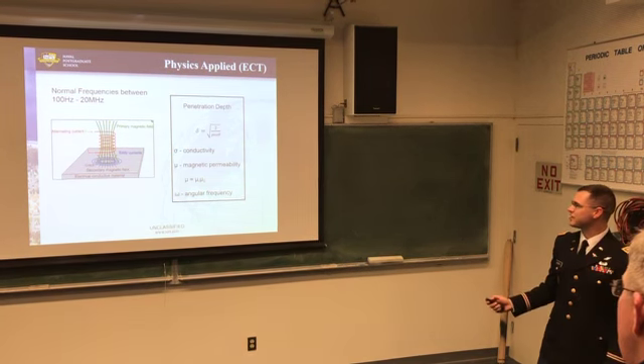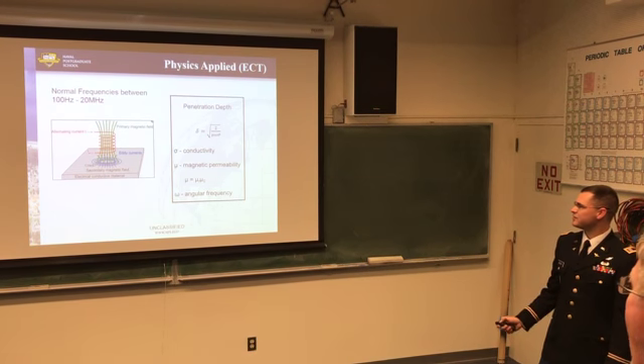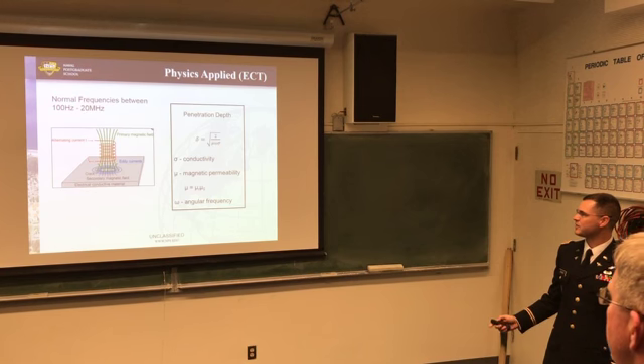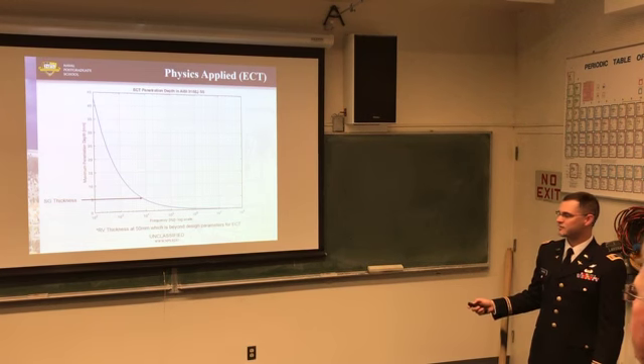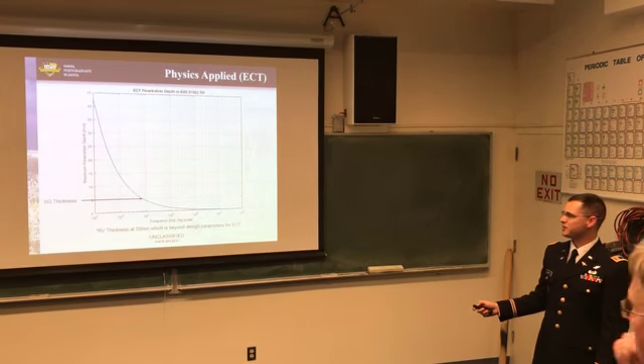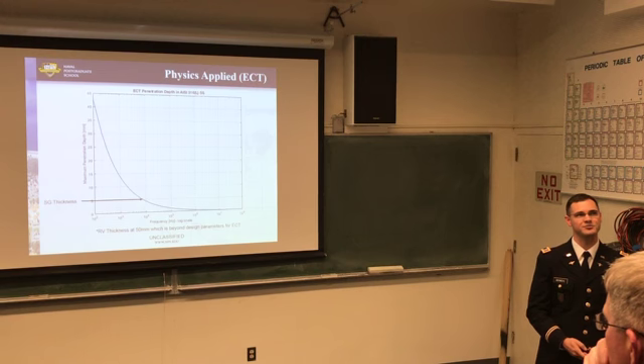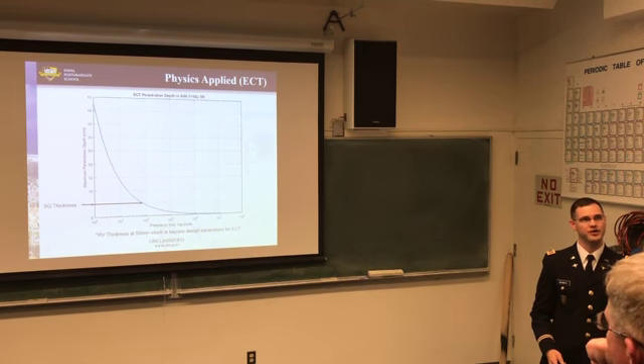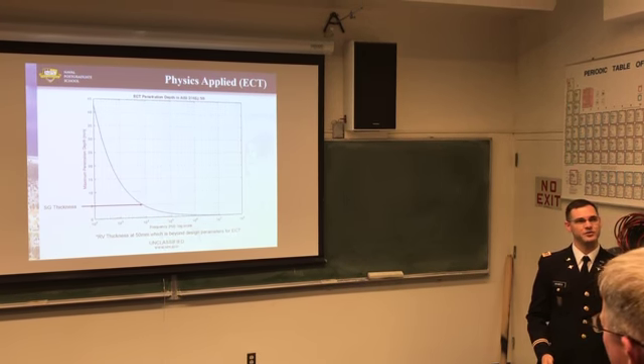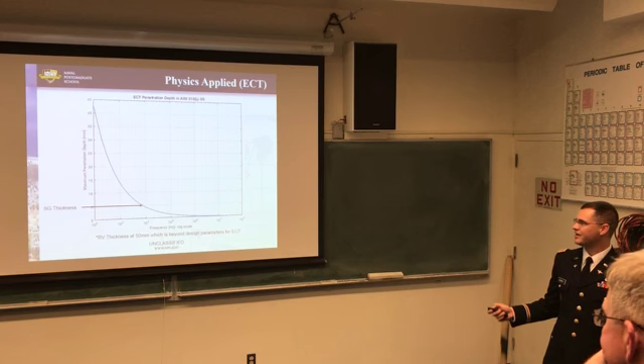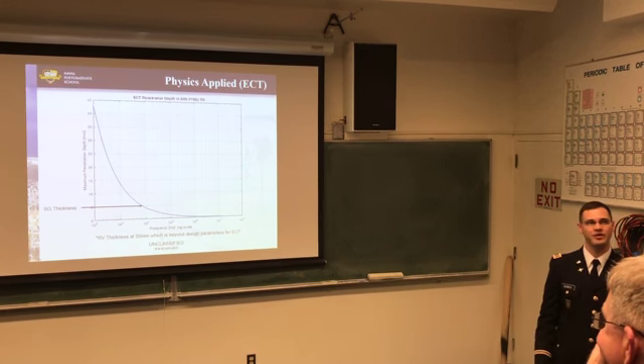There are a few different ways to look at penetration depth, but the one I found the most was the penetration depth based on conductivity, permeability, and angular frequency. And by taking that and graphing the frequency, because everything else is material properties, against your maximum penetration depth, you find that it's very well suited for inspecting steam generators, which have a 5 millimeter thickness. That's great for steam generation, but eddy current testing is also used on the reactor vessel. However, a lot of the reactor vessels are either thinner or they inspect it from the inside of the reactor. And for us, inspecting on the outside of the reactor vessel comes just outside the parameters for normal eddy current testing. So then we start looking at ultrasound.